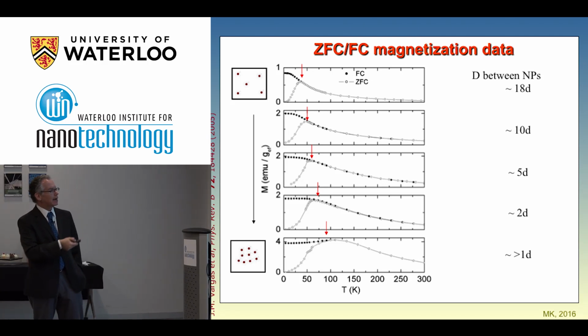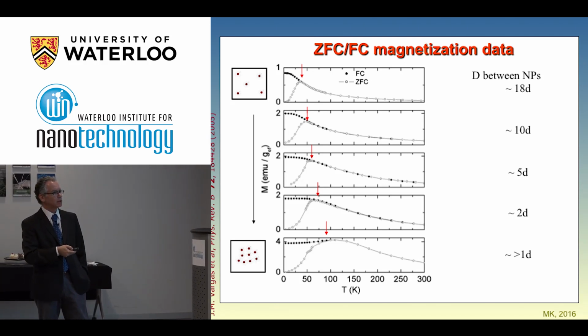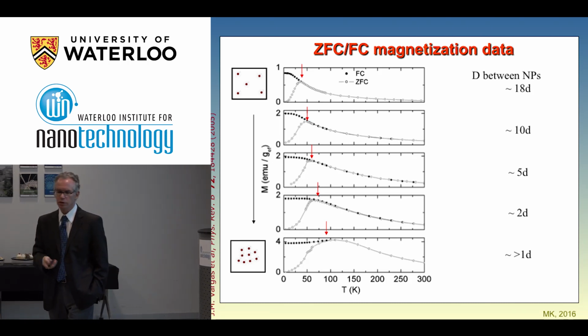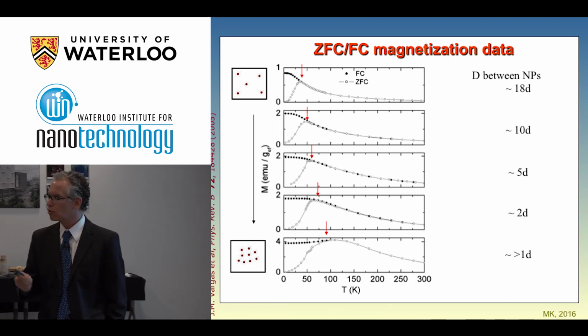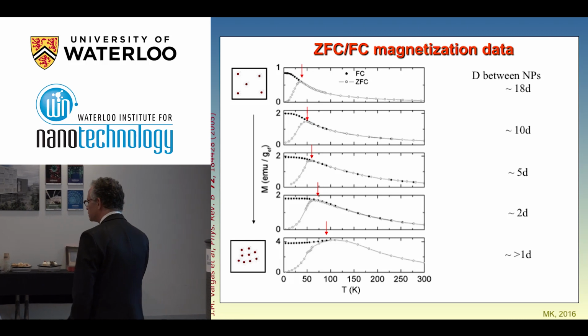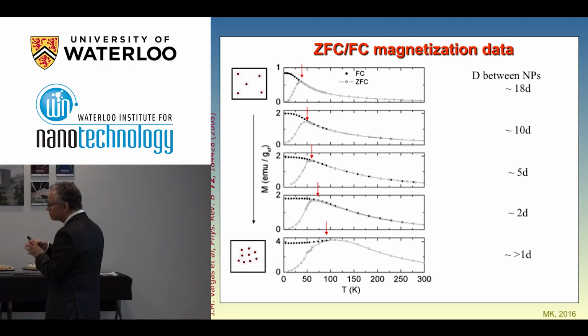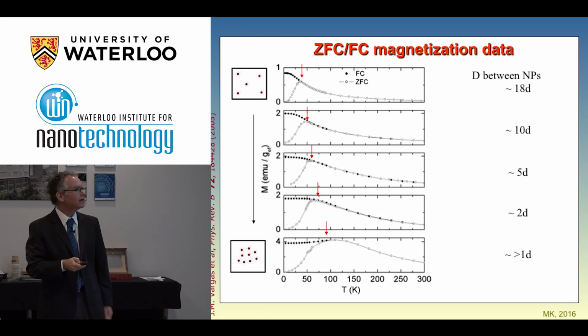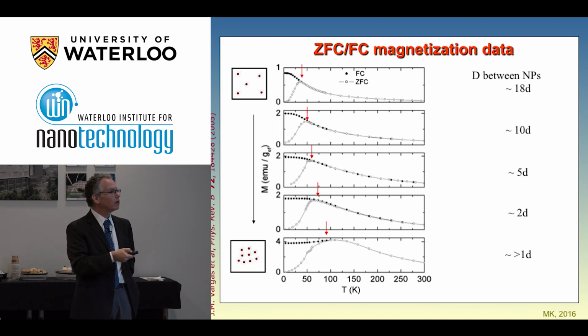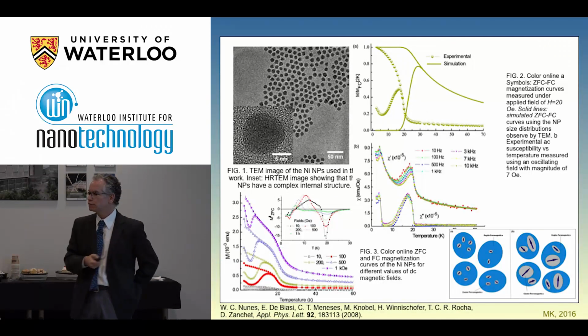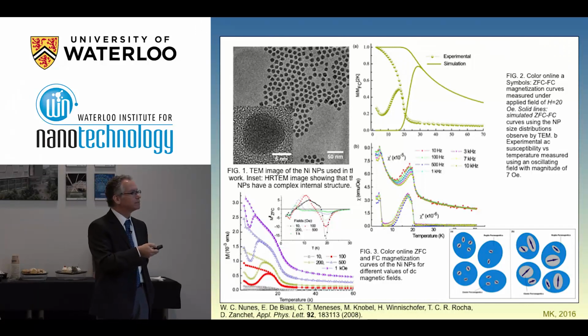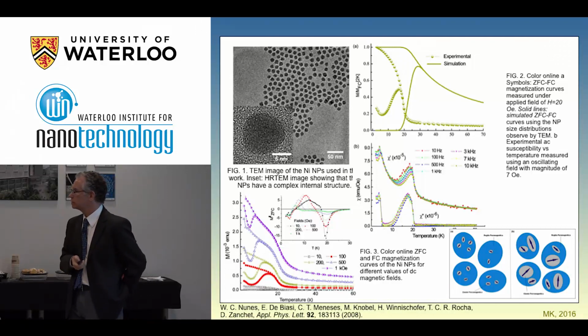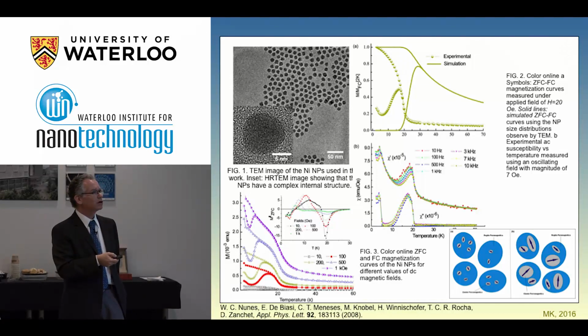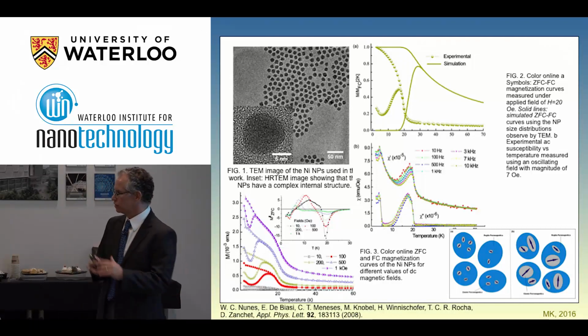But of course, this is an ideal system, an ideal problem. And also, as you probably already know, whenever you start working on a problem, a more complex problem appears. So it's always like that. So we started trying to make very good samples and very controllable and so on. And suddenly, we wanted to go from cobalt, and then we made a nickel sample, and apparently we were able to make very nice and very stable amorphous nickel nanoparticles. And whenever you measure now the magnetic properties of the nanoparticles, they have a completely strange magnetic behavior. We still don't understand very well.